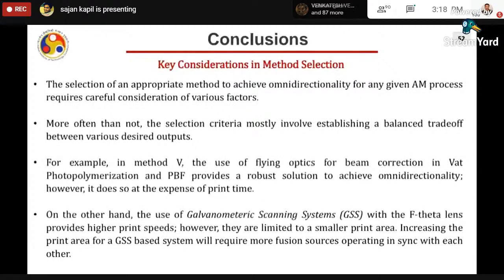On the other hand, the use of galvanometric systems with f-theta lenses provides high print speed, definitely, but they are limited to smaller print area. And that is why we all have a limited print area in the powder bed technology. Usually they are limited to 300 by 300 by 300 millimeter. Height doesn't matter, but the XY is something really important. They really can't go with a single laser beyond 300 by 300 by 300, and that too is the largest, I think, by DMG Mori. Otherwise, they are limited to 250 by 250 by height can be anything, but usually 250.